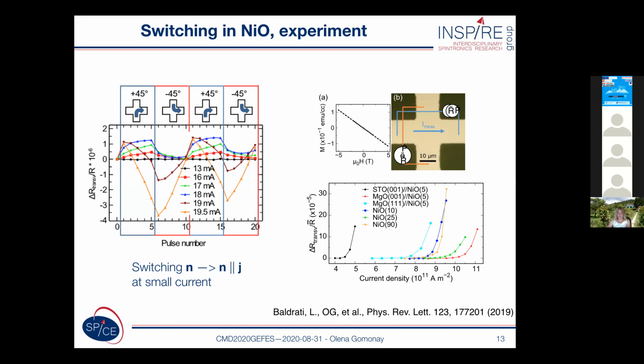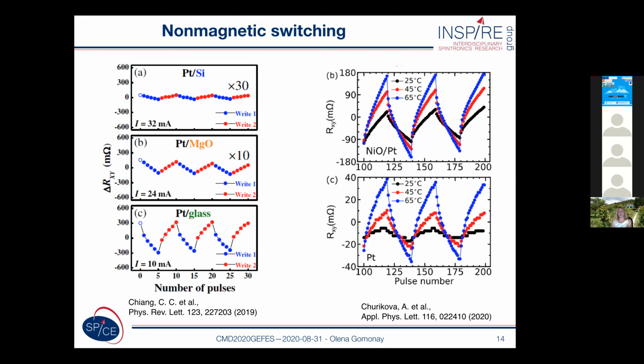However, when we returned back to our experimental data, we have also seen some additional problem, which was also mentioned in the previous talk. So for small current densities, the direction of switching was consistent with the theory prediction. So the Néel vector was switched parallel to the current direction. However, for large current density, the direction of switching was opposite. It was surprising, but at that moment we were aware of the works which claimed that there is some dependence of the platinum resistance versus current, which is related simply to electron migration processes, so some electrical phenomena within the platinum electrode. And these phenomena, of course, can change the whole picture of switching at a high current density.